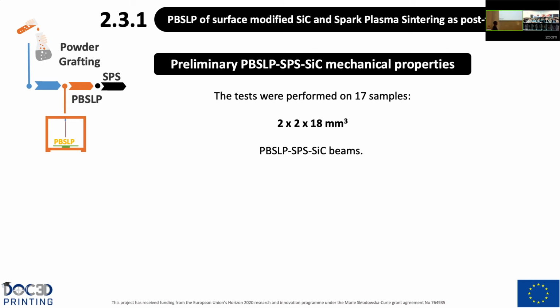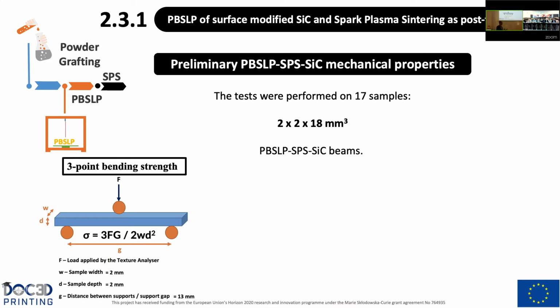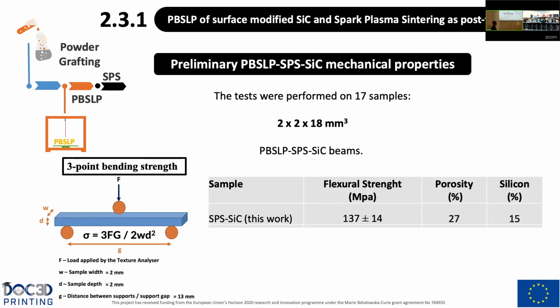So next, we performed some preliminary mechanical properties tests, but actually here we had time just to test the silicon carbide and not the surface modified silicon carbide. We were using 17 samples with these dimensions. And first, we wanted to study the flexural strength by using 3-point bending tests. Specifically, we obtain a value of flexural strength of 137 megapascals.